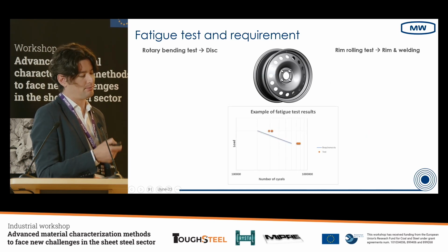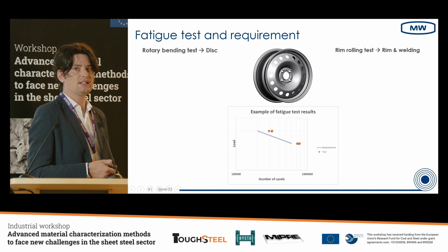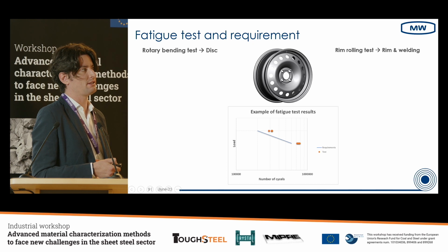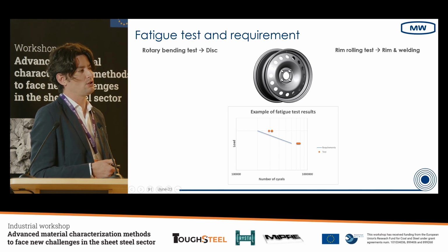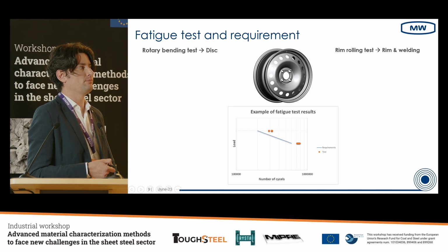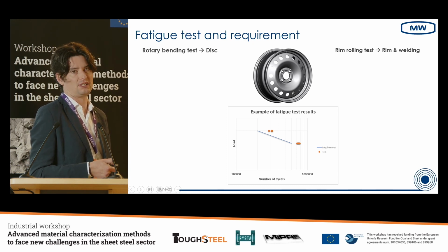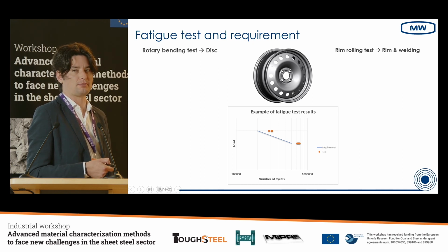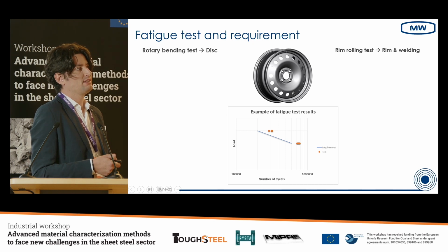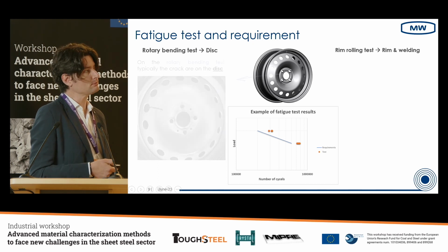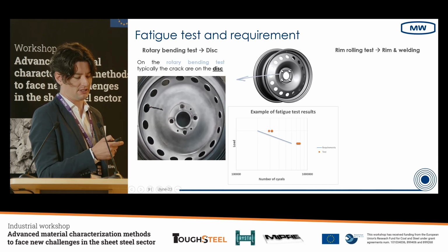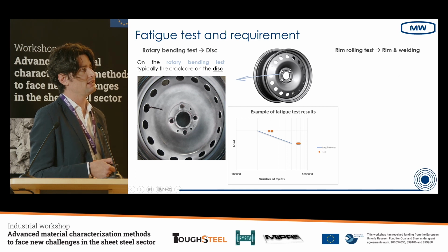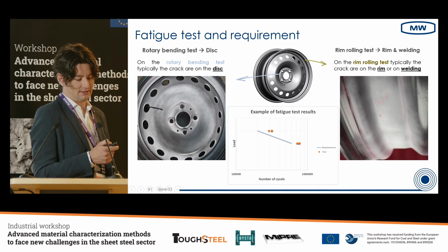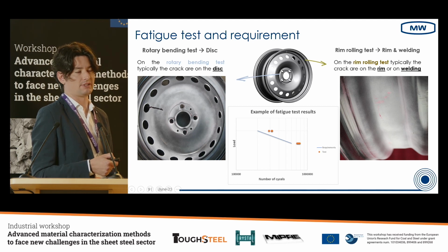In this graph, there is an example of what is required by the customer. Usually the customer requires one or two levels of loads. Here it is generically loads, but it can be bending moment in Newton meters or radial forces in Newtons, and a minimum number of cycles to respect. The test is okay when the wheel exceeds this minimum number of cycles. Here there is an example of a crack on the disc after the test, shown with dye penetrant. And this is an example of a crack on the rim after the rim rolling test.